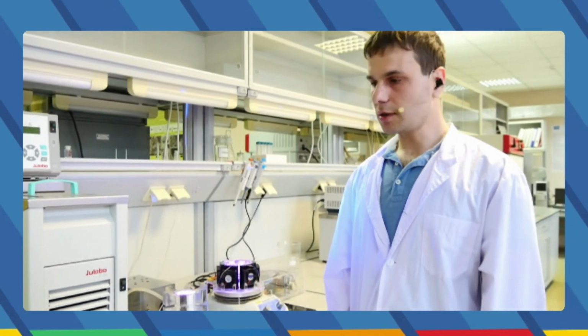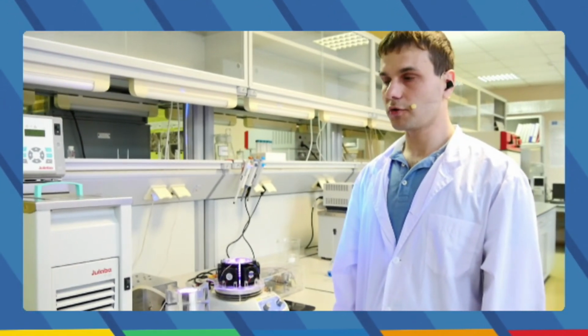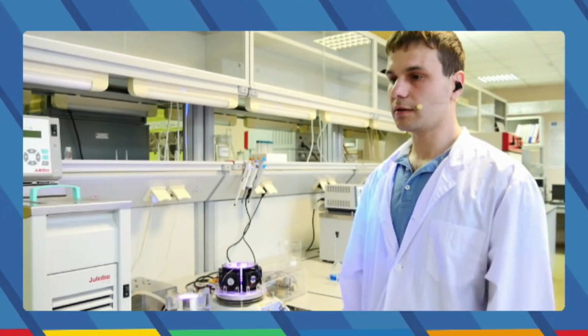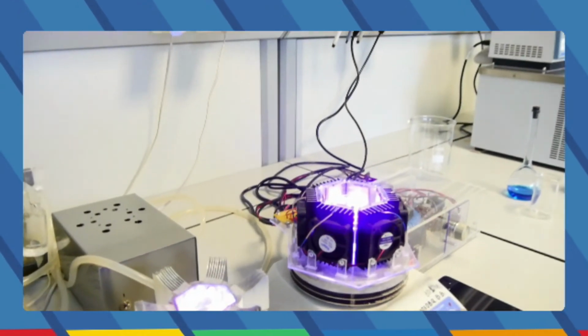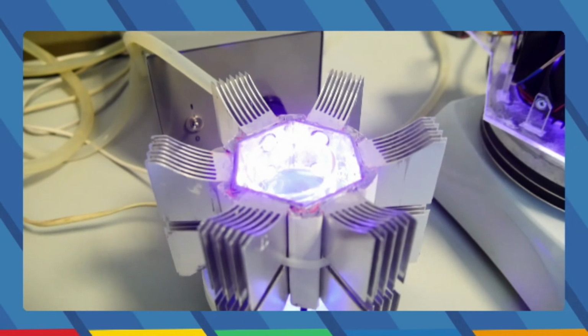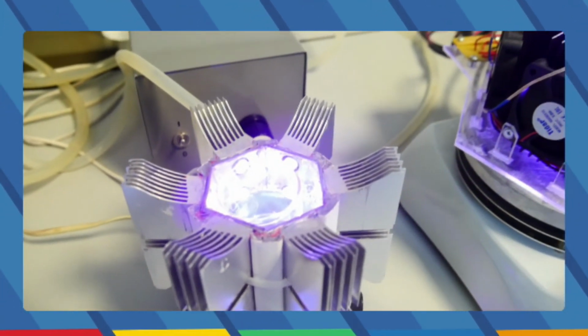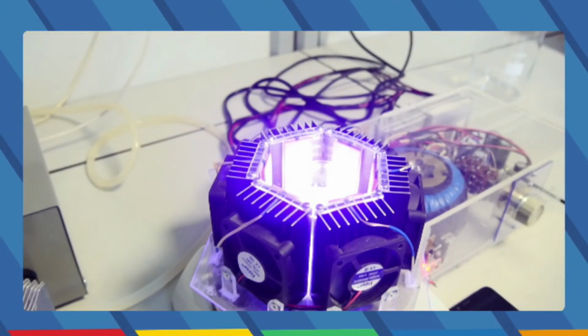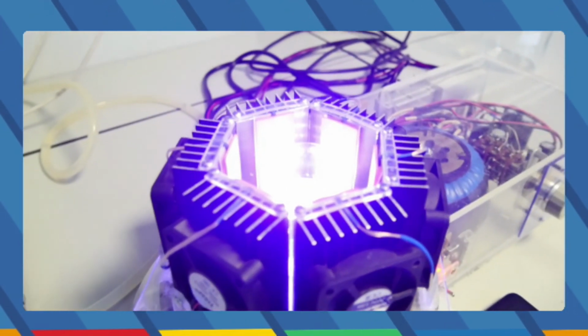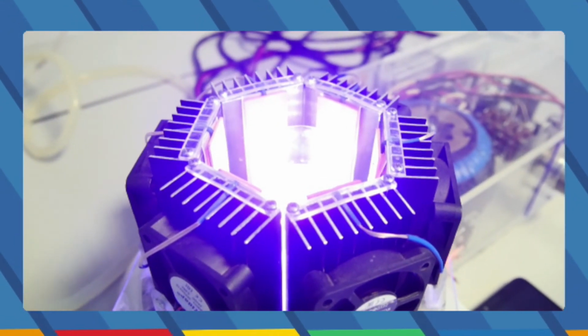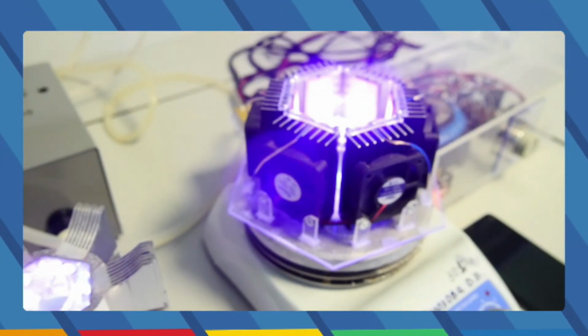So the essence of this preparation way is utilization of titanium peroxide complex as the precursor of titanium dioxide. Firstly, we prepare colloidal particles of titanium dioxide, then we dissolve them in hydrogen peroxide with formation of a transparent orange or green, depending on pH value, solution of titanium peroxide complex. Then afterwards we can prepare our particles with desired size through different ways. We can precipitate our spherical particles by exchange of the solution. This phenomena occurs because this complex is not stable in organic solvents, for example methanol, propanol, and so on.